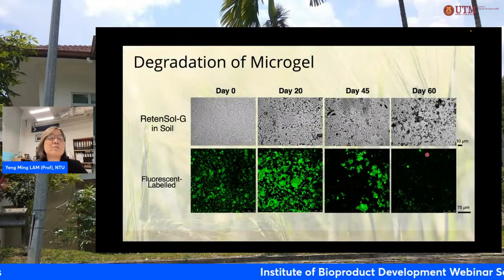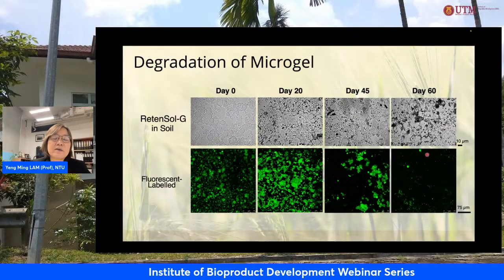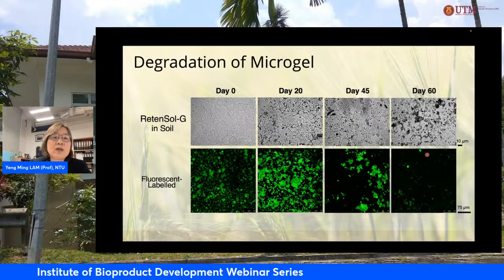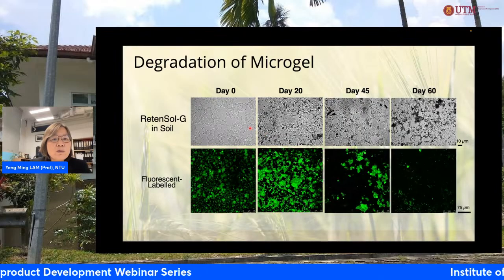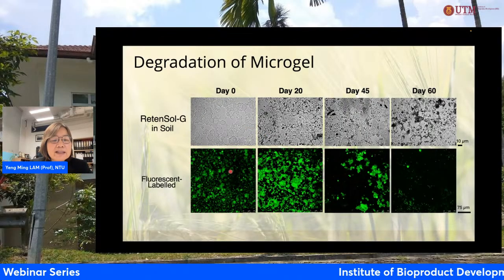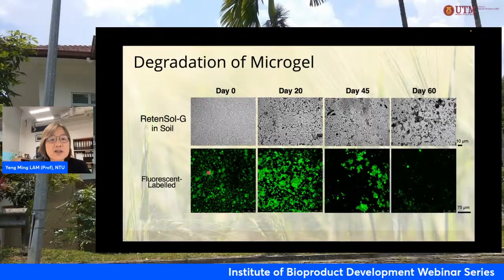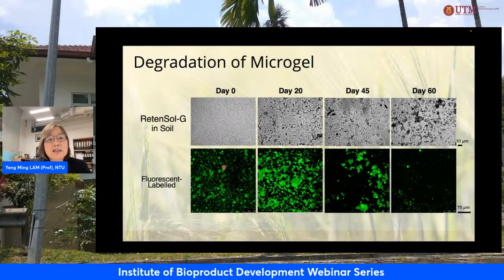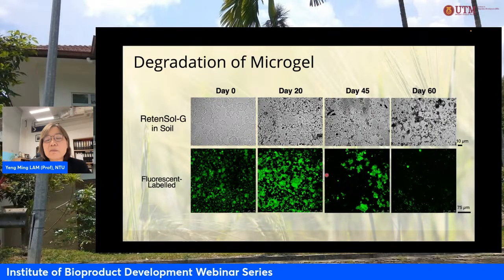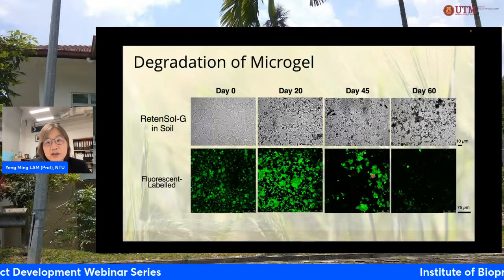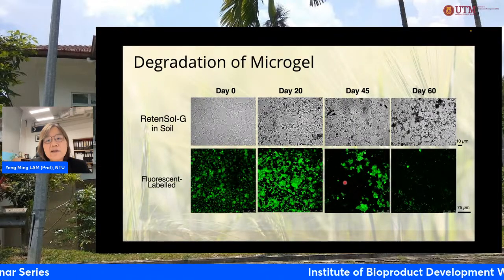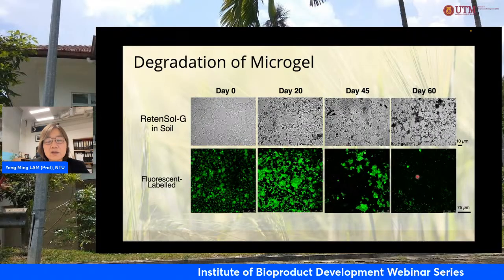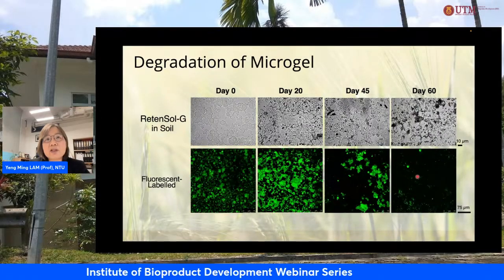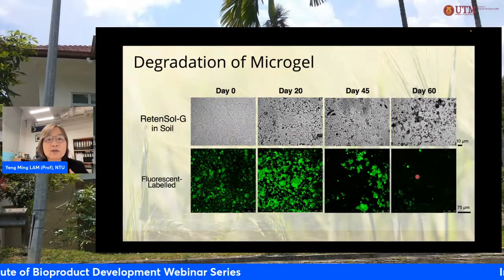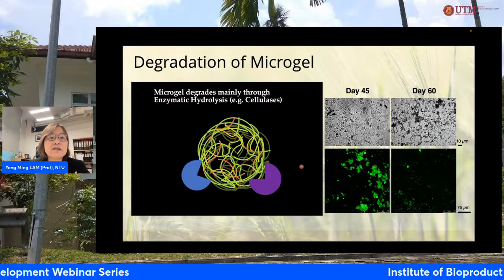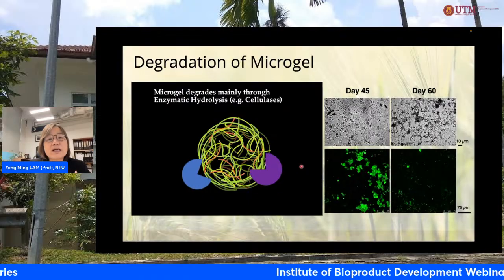So what happened to the microgel in the soil? I mean, a lot of questions was asked, whether do we know if it's actually degrade? So this is what we did. We follow the microgel existing in the soil, what happened in the soil. So this is actually fluorescence labeled gel. So in day 0, this is the amount. Day 20, this is still the amount. Day 45, you start to see the reduction in the greenness. This is actually the gel, and then the less of the gel. By day 60 is all degraded. So the beauty of this is actually this microgel is consumed by the cellulase that's actually present. The microgel is actually degraded by the enzyme present in the soil.